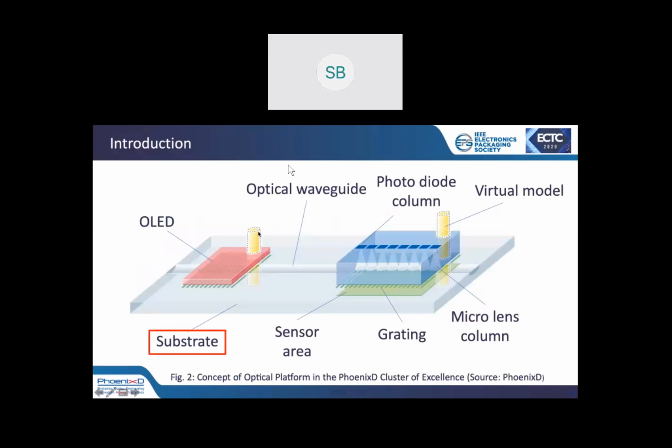research topic. On the right side, you can see a confocal image of an optical waveguide structure of our master mold. You can see it has a high surface quality. If we look at the surface evaluation of the plastic parts, we can see an increase of the surface roughness, which is still very low. On average, concerning our best structures, we have about 30 nanometer roughness.